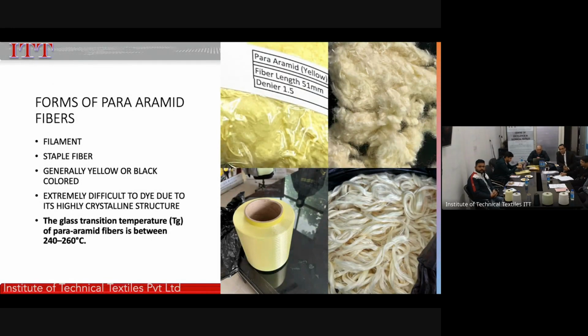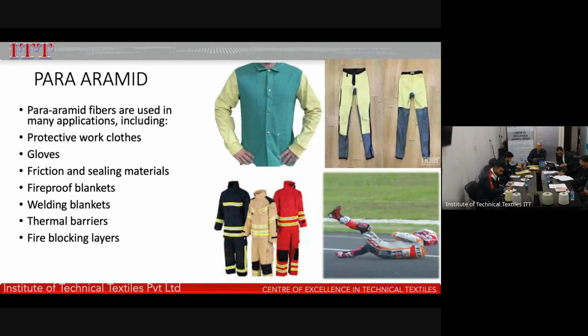Again, para-aramid is available in filament form, staple. Generally, yellow or black. It is extremely difficult to dye because of its highly crystalline structure. The glass transition is around 240 to 260 degrees centigrade. Now, para-aramid fibers are basically used for protective workclothes, gloves, friction and sealing materials, fireproof blankets, welding blankets, thermal barriers, and fire blocking layers.